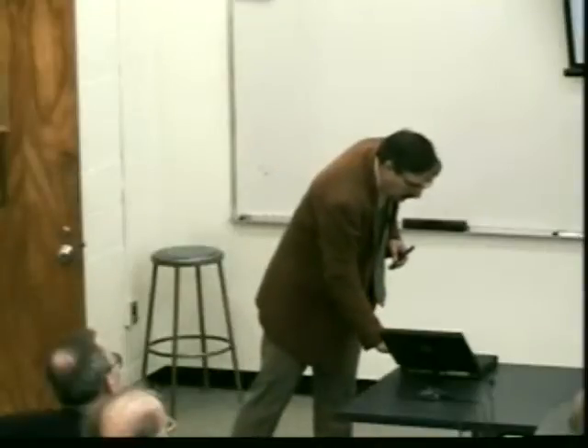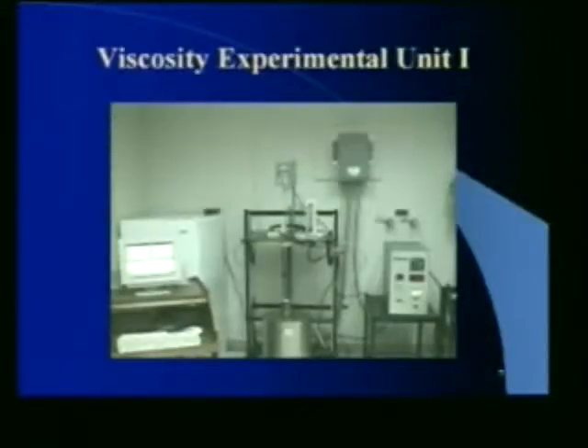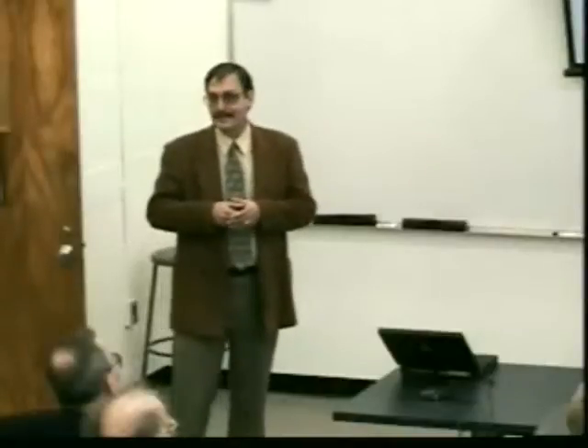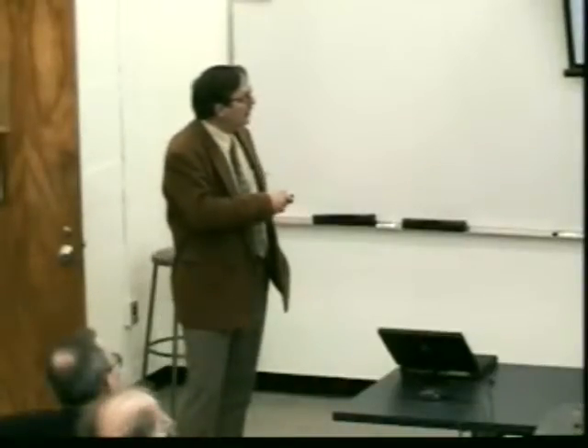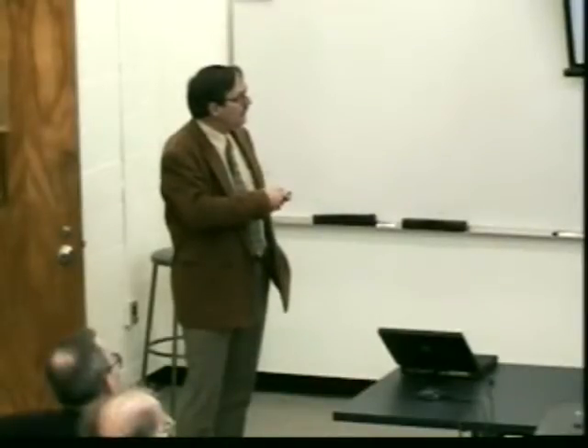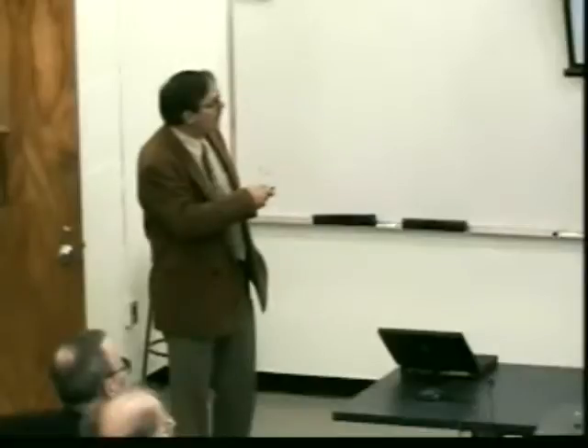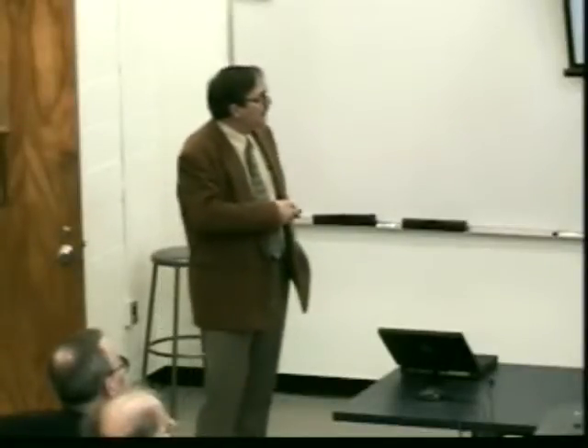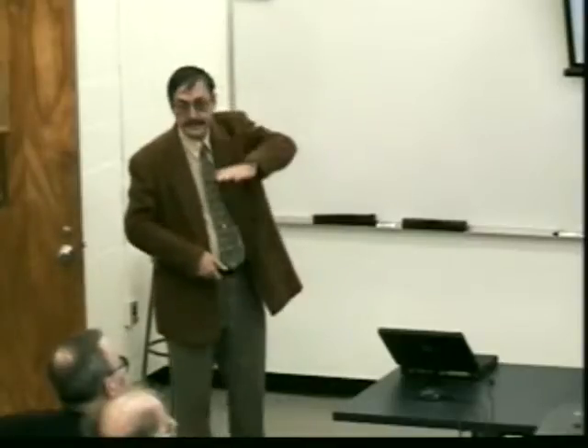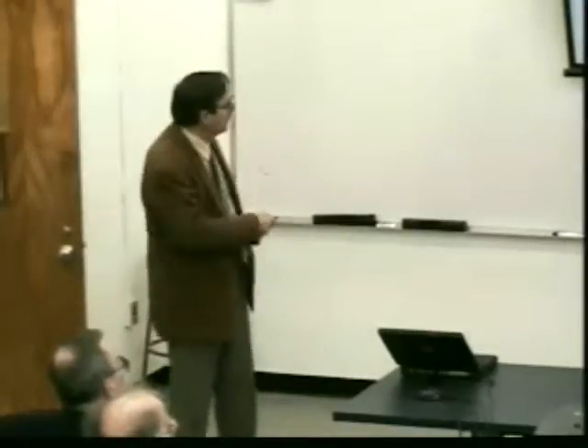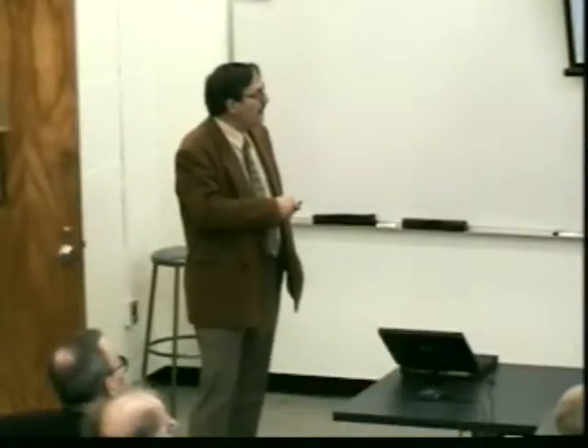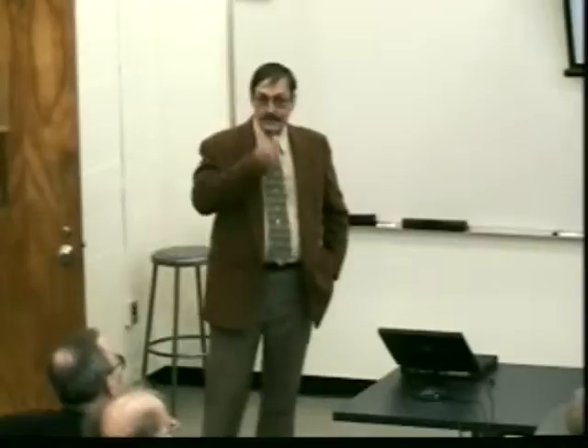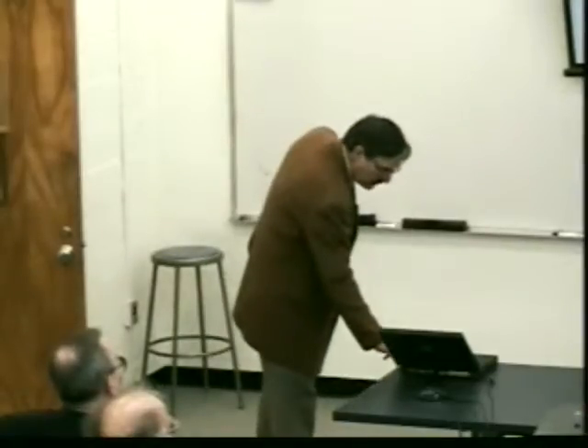And so we built a viscosity unit, and that's shown in a picture here. This furnace is a molybdenum disilicide element furnace, and it goes up to about 1700 centigrade. So it allows us to measure viscosity theoretically up to about 1700 centigrade. Shown here is a controller, but this graphite part here is really a support system for a crucible that sits here, and then the viscometer is shown coming down through here. This whole thing is on a movable platform that allows us to position the viscometer at the right level into the system, and then the data is taken here. This is a lot harder than it looks to build a system that operates up to these temperatures, but this is an example of a high temperature system for high temperature viscosity.